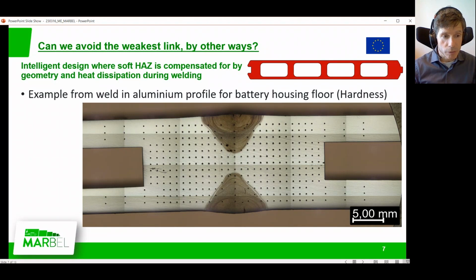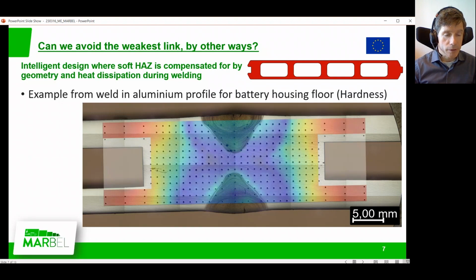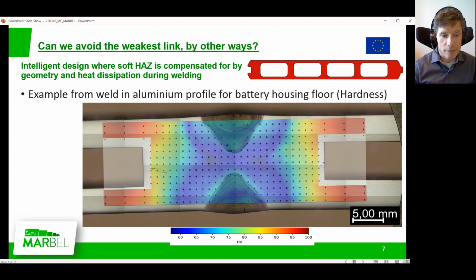and the heat affected zone is then distributed like this. Here you can see the blue area representing the weak areas where it's very soft, and the red is the full strength areas further away from the weld zone. By accounting for the geometry with the geometry for the heat affected zone, we can compensate.